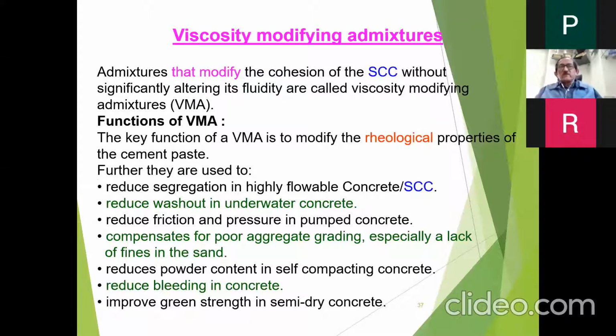Viscosity modifying agents are the admixtures that modify the cohesion. Their functions are the rheological properties. They modify the rheology. Further, they are used to reduce segregation, to reduce washout in underwater concrete, reduce friction and pressure in pumped concrete, compensate for poor aggregate grading, especially a lack of fines in the sand, reduce powder content in self-compacting concrete, reduce bleeding in concrete, and improve green strength in semi-dry concrete. So all these things give viscosity modifying agents their place in self-compacting concrete.